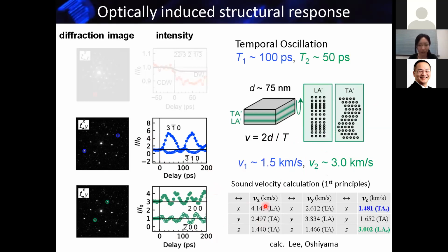We first calculated the sound velocity, and then we found that this slower oscillation corresponds to the transverse acoustic phonon, and this faster oscillation corresponds to the longitudinal acoustic phonon. So from this time period and the thickness of this sample, we can estimate the sound velocity like this. The strain pulse travels back and forth along the sample thickness, and it appears as this oscillation. We estimated the sound velocity from the experiments, compared it with the calculation, and found a very nice agreement.